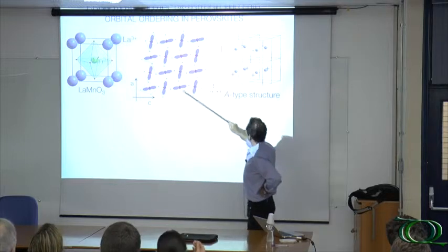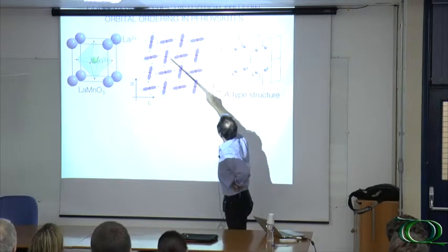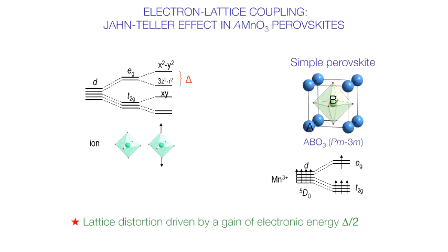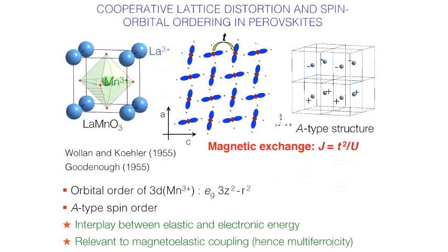So here, typically, you have a ferromagnetic coupling, and you have a zigzag pattern of orbitals. This is the dz squared minus r squared orbitals, the 3z squared minus r squared orbital, right, which has a shape of a double cigar, which is occupied when you have a 3+ manganese, so you have a Jahn-Teller distortion, and in order to minimize the energy, the structural distortion is accommodated in this zigzag shape, which also implies, because of the super exchange theory I just mentioned, a ferromagnetic coupling within the AC plane.